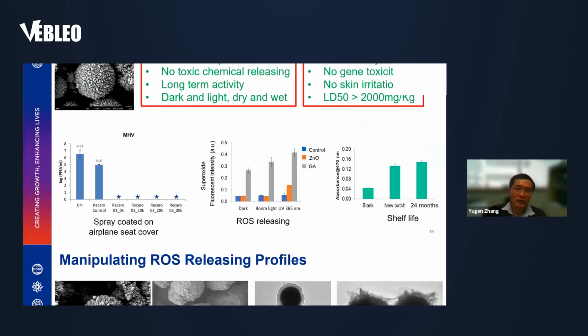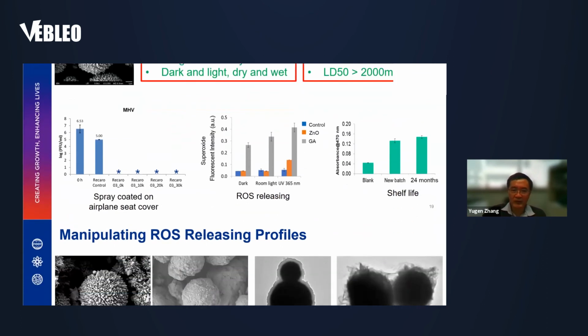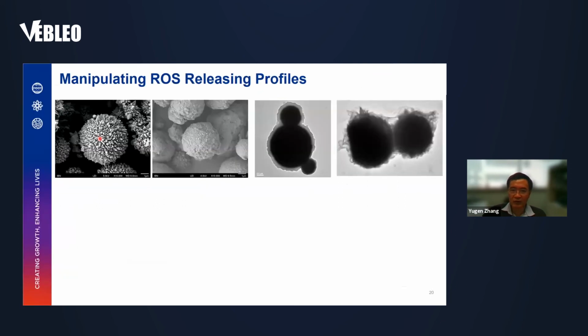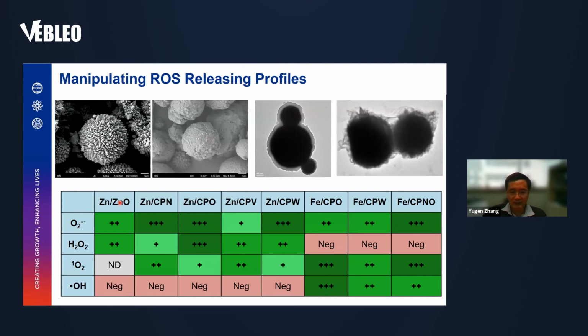And we can also manipulate or change the component or structure of this core-shell material to achieve different functions. And showing here, there are different types of core-shell materials. Some of them can release more superoxide and hydrogen peroxide, as shown here. But some others can release more singlet oxygen and hydroxyl radicals. So by doing this, we can really choose different materials for different applications.